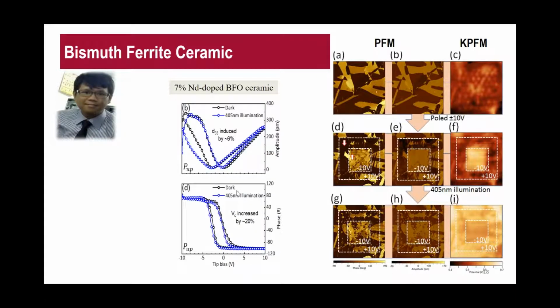So we have the graph shown here. This is also obtained from PFM, indicating that the piezoelectric coefficient can be increased by 6% with light illumination, and the coercive field voltage can also be increased by 20% based on the PFM measurements. The sample here is a 7% Nd-doped BFO ceramic, and this is very important information. Supposing you are using the materials for photovoltaic applications and for other sensors and actuator devices, how would you like to enhance your materials by external sources? This might be very good information for engineers to select the materials for the right application.